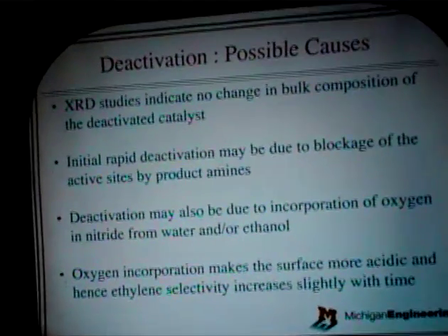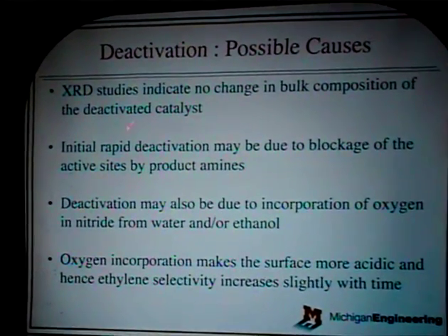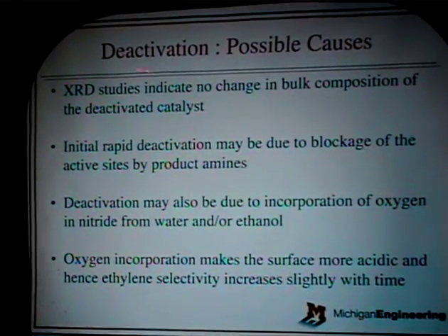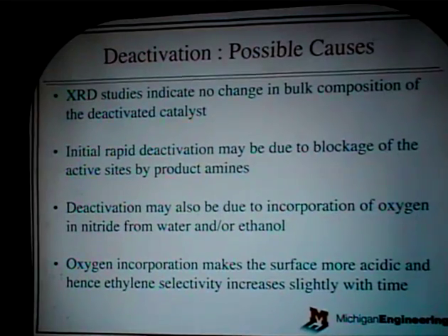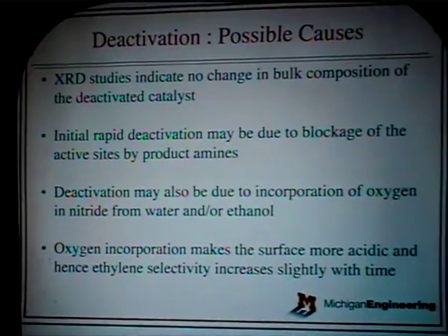Now, we did the XRD studies of the deactivated catalyst after use, and we didn't find any change in the phase composition of the used material, that is the deactivated material. And we have carried out the surface area study also, and there was a negligible decrease in the surface area of the used material.